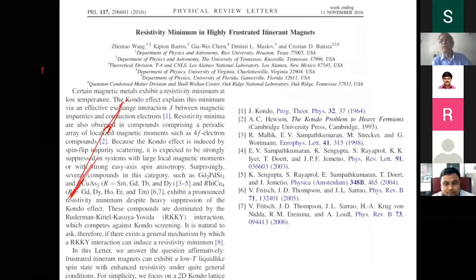In other words, when the rare earth ions sitting on triangular lattice are antiferromagnetically coupled, they give rise to some extra scattering in the metallic situation that can give rise to an upturn. This is the very substance of this paper. So the new concept is evolving that Kondo effect, which is traditionally known to give us resistivity minimum, is not the only concept which can give rise to resistivity minimum.